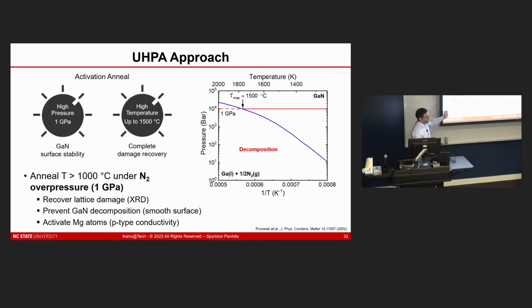Now, if you're involved in this area and you've built tools before, you probably realize this is a gigantic number. So there are very few places in the world that will do this for you, and we're lucky enough to have a collaboration with a team at the High Pressure Institute in Poland where we send our samples, and they have a system set up for being able to do this. So effectively, at these high temperatures, we can go up to 1,500 degrees at high pressure and prevent decomposition of the GaN, and then look at recovery of the material and activation of the implanted magnesium.